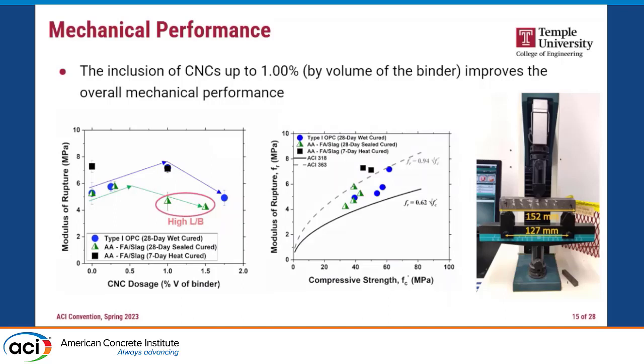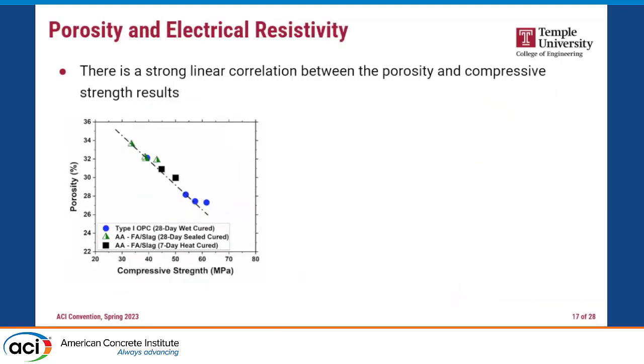This is the compressive strength versus the flexural MOR, right? And we compare with the ACI equation, so you can see the heat-cured alkali activated is a very ductile system, even if it performs as a high-performance concrete. And that's a CNC mix we tested. Even the CNC mix with 1.00% showed very promising results, a 30 to 40% increase in the modulus of rupture.